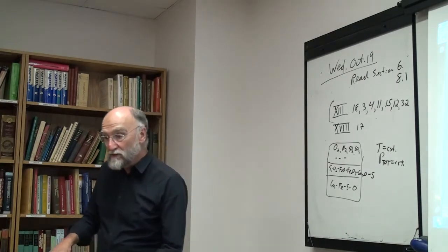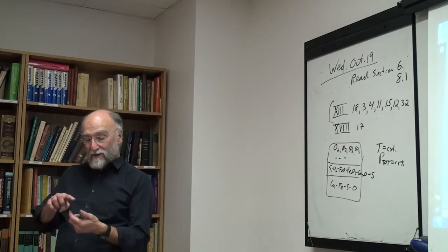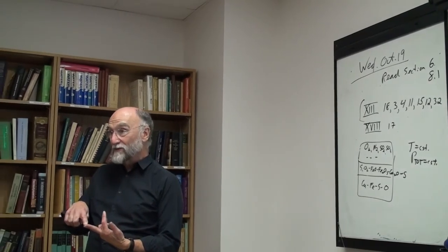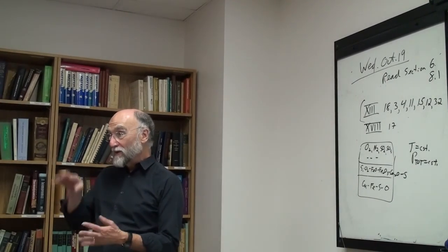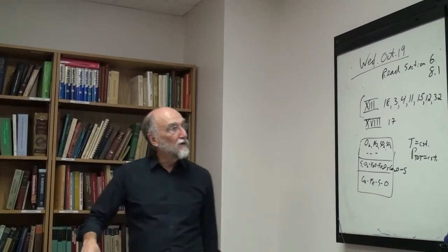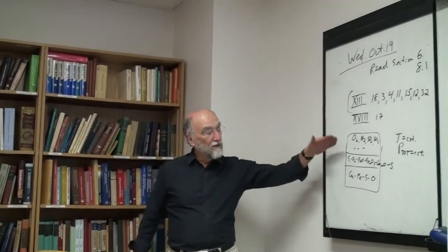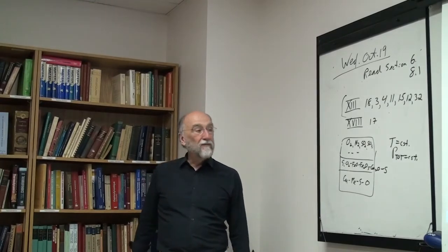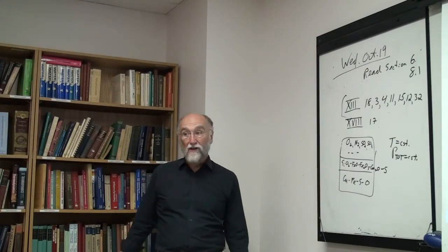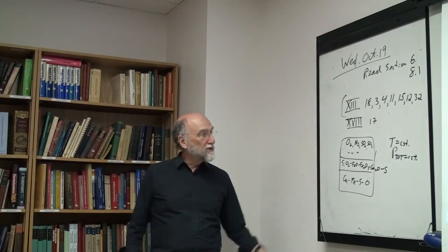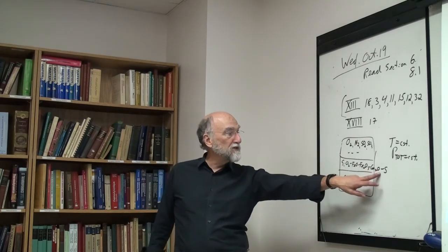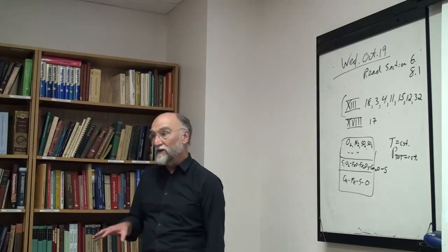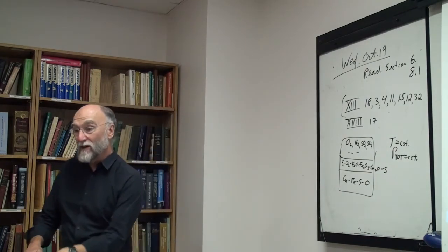Remember when I talked about the phase rule, I said there are phase rule variables: temperature, pressure, chemical composition of each phase, not total composition, but phase compositions, and so on. These are your variables. So if your degrees of freedom is 0, then all the phase diagram variables have to be the same everywhere. But the total amount of each phase is not a phase diagram variable. Okay, so PSO2, PO2, weight percent sulfur in the slag, temperature and total pressure, is that enough to completely define the system? In other words, is the number of degrees of freedom 0?